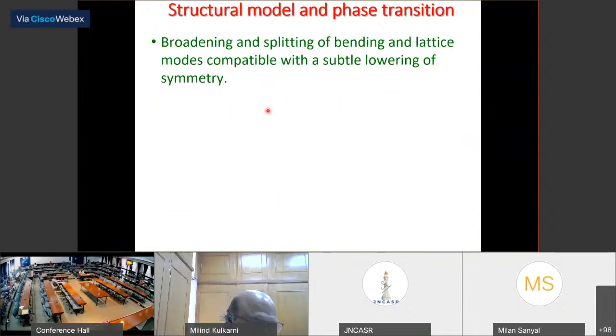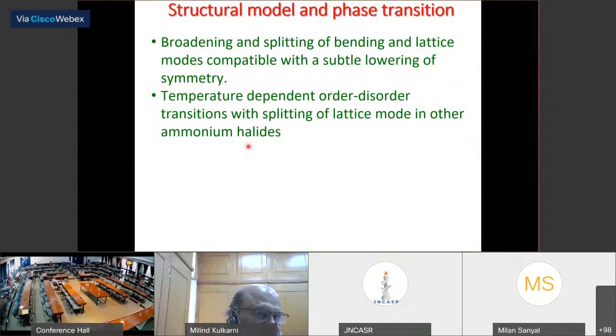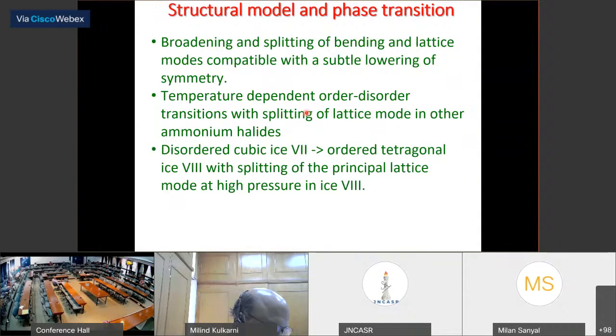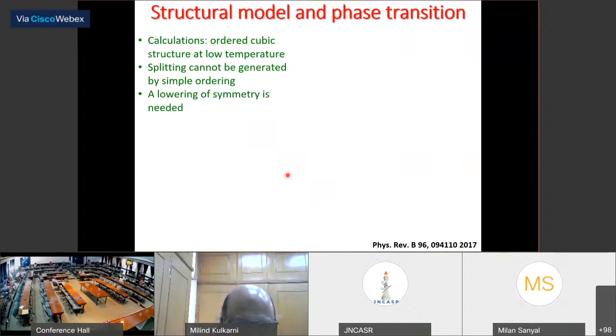Now, what is the actual thing happening in the system? The broadening and splitting of the bending mode cannot happen without lowering the symmetry. So it is not cubic, something else is happening. The temperature dependence of ice also shows the same thing, as do your ammonium halides: they go through an order-disorder transition. You can see it in ice also. So let us look at it in calculation.